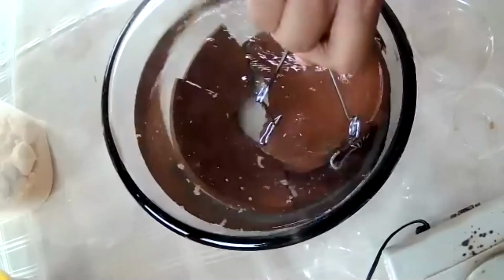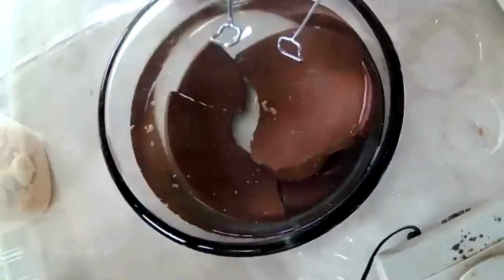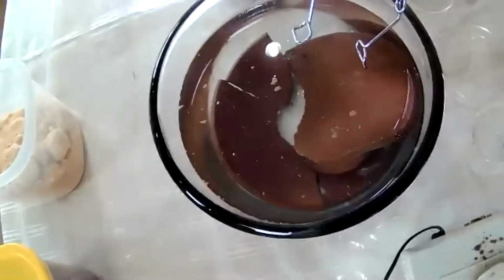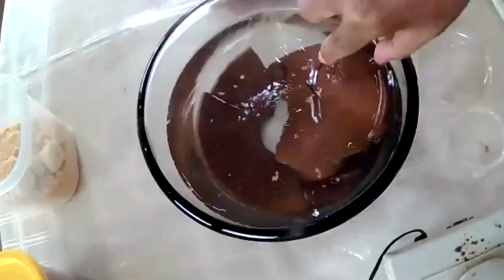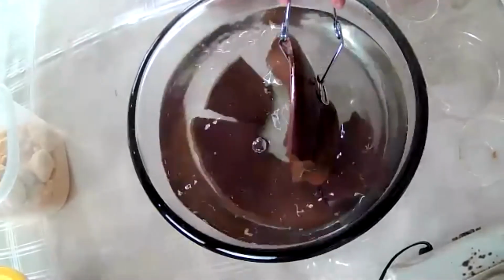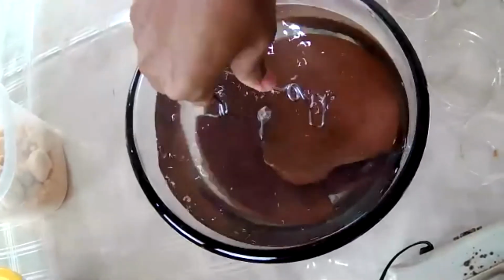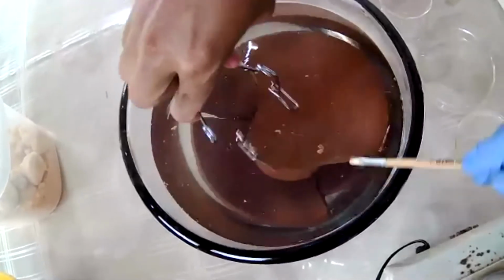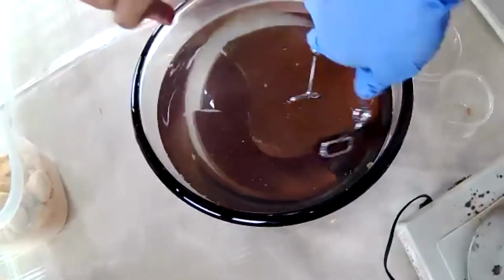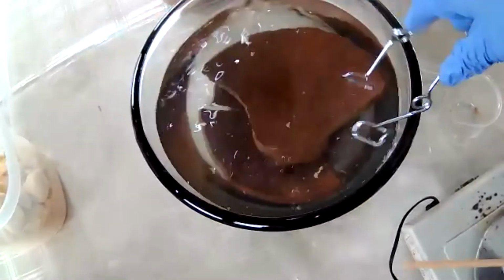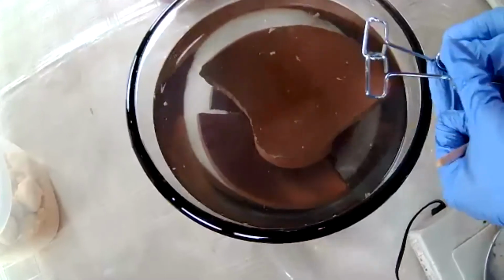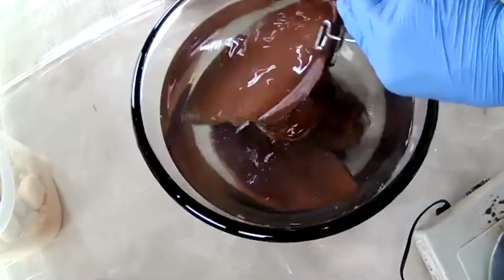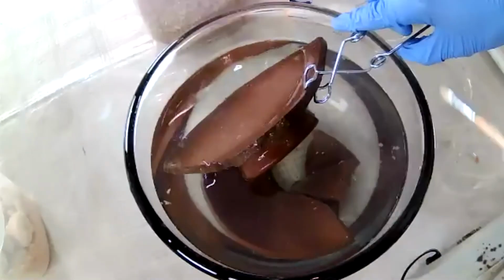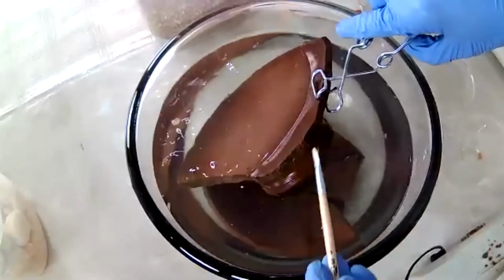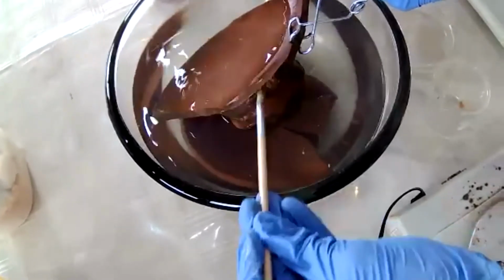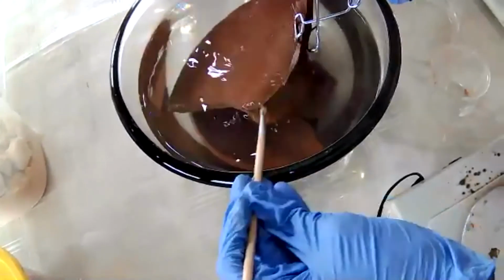If we want to further clean the surface where we applied the adhesive, we just brush it off. We wait until it's soft enough in the water and then we brush it off, and it will be clean again. So the adhesive will not leave any residue on the surface of the fragment. You can see the adhesive floats on the surface of the water. So this is why we said that it's a reversible adhesive.